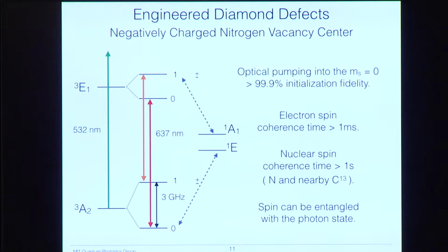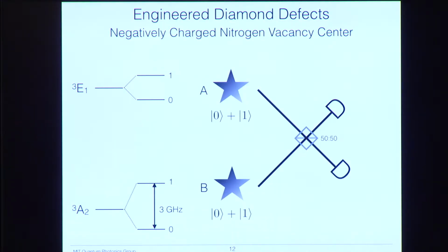And it is this property that we'll use to create entanglement between different NV centers. So let me explain briefly how this works. What we first do is a pulse to create a superposition in the electron spin state between 0 and 1, and we do that for 2 NV centers, so they both have superpositions.